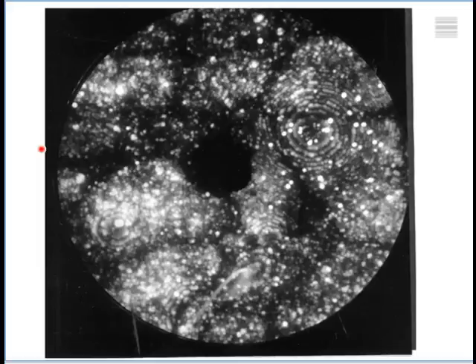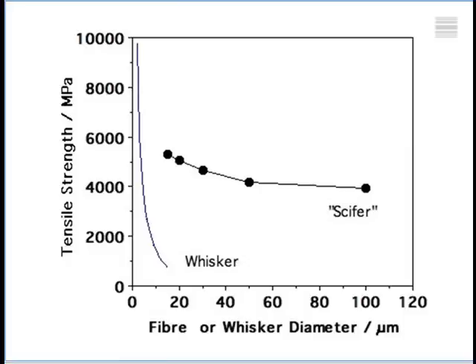Let me just show you that this material is not size sensitive because we are actually gaining strength by introducing defects. So this is the original graph that I showed you from 1950, where the strength collapses as we increase the size. And this is the steel where the strength has been produced by deformation. It is not sensitive to size.